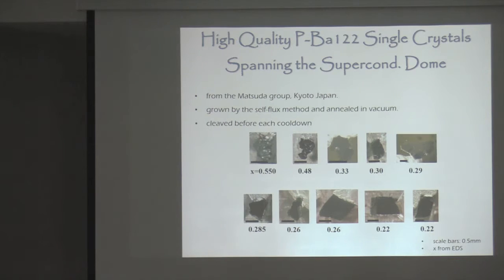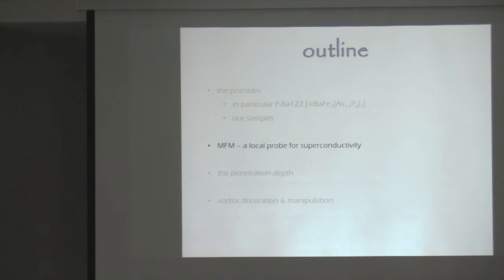Okay. So the samples, here are pictures of all the samples. We had samples from the Matsuda group in Kyoto across the whole superconducting dome, so pretty low doping to pretty high doping, going through near optimal doping. And we did a set of measurements on each of them. Okay, so next I'll tell you about the probe.